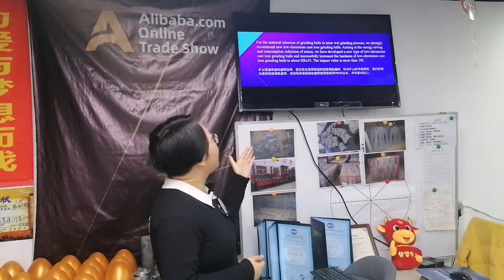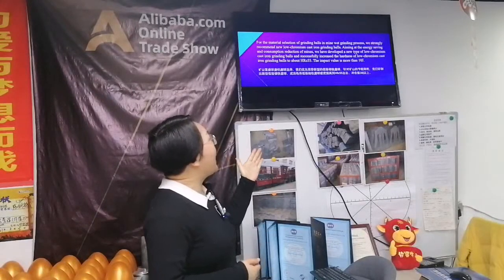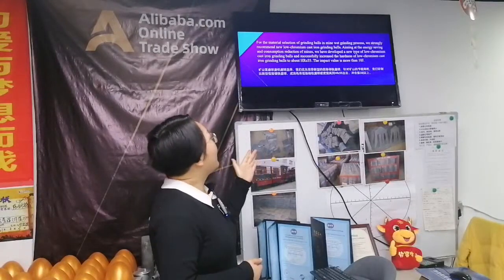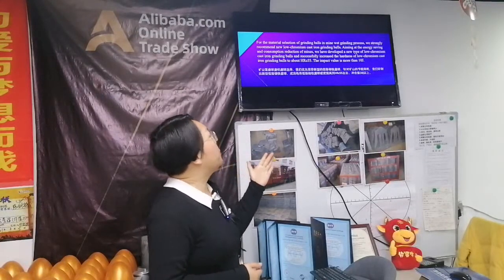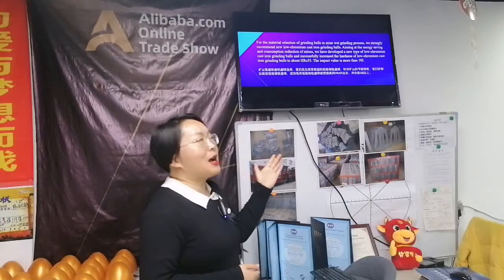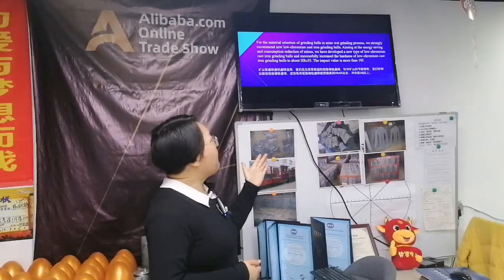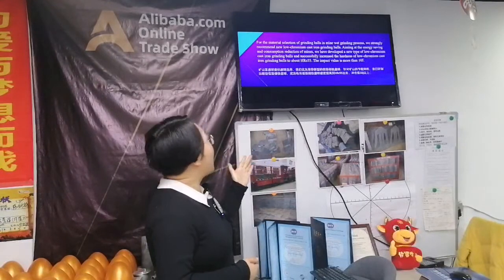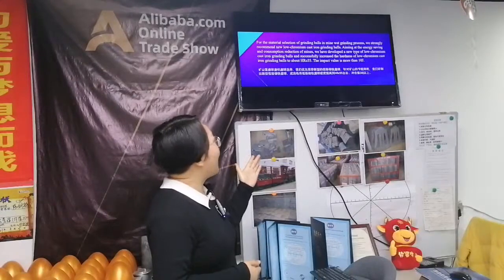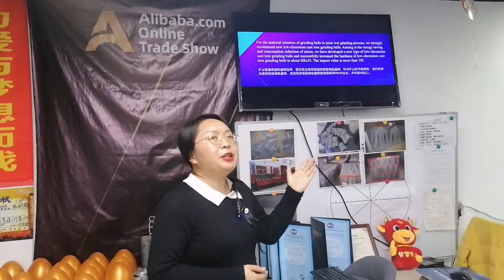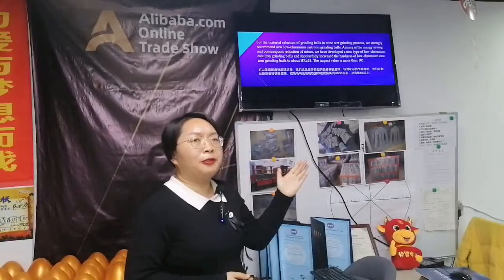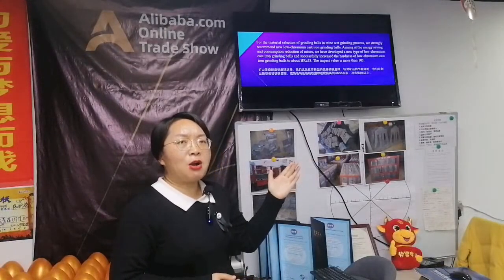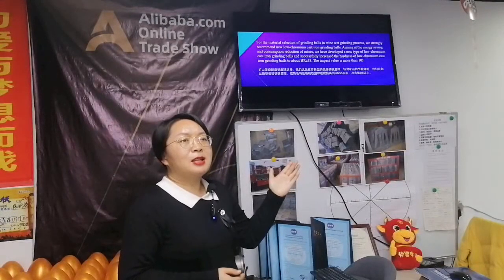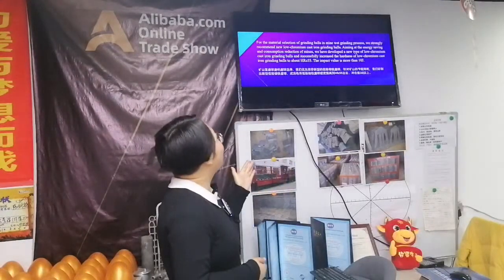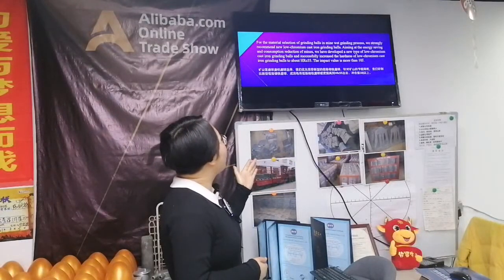For the material selection of grinding balls in mine grinding process, we strongly recommend new low chromium cast iron grinding balls. Aiming at the energy saving and consumption reduction of mines, we have developed a new type of low chromium cast iron balls. The chromium is about 2%.